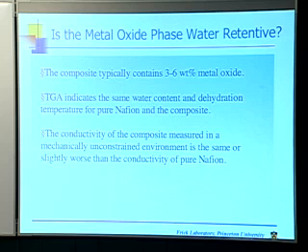And by the same argument, there's not enough material here really to change the water retention properties, per se, of the Nafion. That is, even if you say, well, one of the materials you're adding is silica, and we know silica gel is great at retaining water, it's not enough silica gel to make a difference. It's only a small amount of silica gel. And second of all, even if that's what it was doing, that would be a big problem, because the way metal oxides retain water is they chemisorb onto the metal oxide surface, and they get fixed there. They're stuck there. And we need mobile water that can do proton transport. We need those waters to be able to reorient so that the protons can hop from one to the next. So the kind of water that a metal oxide is going to retain isn't the kind we want anyway.